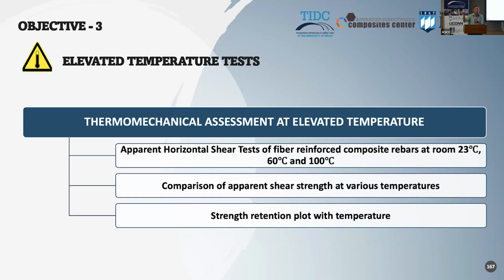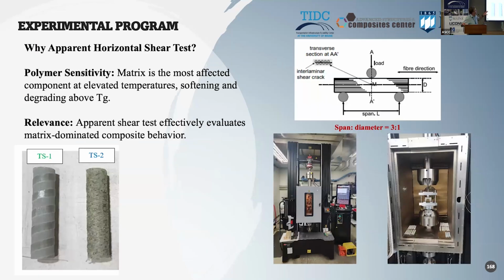We'd like to look at performance. I mean, how the materials behave at higher temperatures and put the requirements in terms of performance. Then whatever material meets that performance, that material will be good, okay? So it would not be tied to a prescription on a particular resin, but it will relate to how the material behaves. I'm going to give you a very quick overview. Yep. So what we do is we run tests with an environmental chamber inside the testing frame. We look at a test that discriminates very well the performance at high temperature, and that is the horizontal shear by 3-point bending, because it looks at the interface between fibers and polymers.